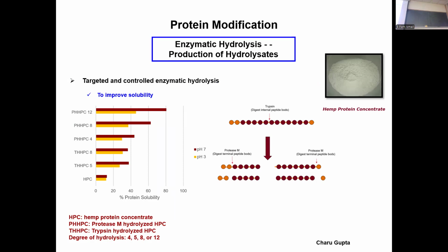But in this study, we looked at not only an endoprotease, we looked at something we use in the lab that is an exoprotease, where it really chops at the terminal end, one or two amino acids at a time. So we increase the charge by doing so, but we don't break the peptide into smaller, more hydrophobic polypeptides. So the solubility with this protease was increased quite a bit. If you look at pH 7, we got about 8 times better solubility. And in this case, we also inactivate the enzyme at pH 3 and 75, I think, degrees, and were able to inactivate it and still maintain solubility.